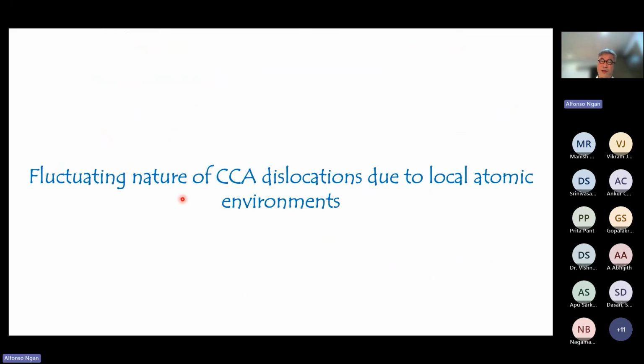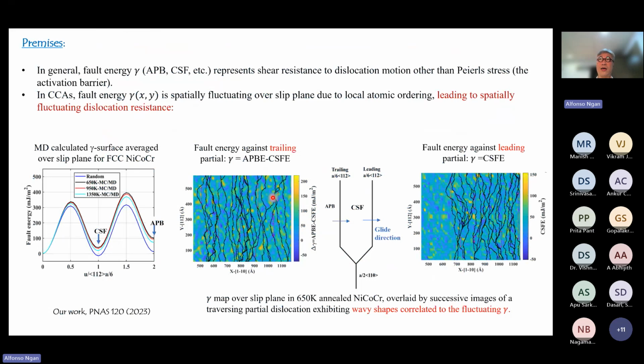So I'm going to talk about the fluctuation nature of dislocations in CCA due to the local atomic environment. Just to give you some idea of what sort of fluctuations we can be talking about. In general, let's say we take the leading Shockley partial of an FCC dislocation into consideration. As this dislocation moves forward, it will trace a new area of stacking fault, which is called complex stacking fault. And so the resistance of that movement can be well represented by the value of this fault energy gamma.